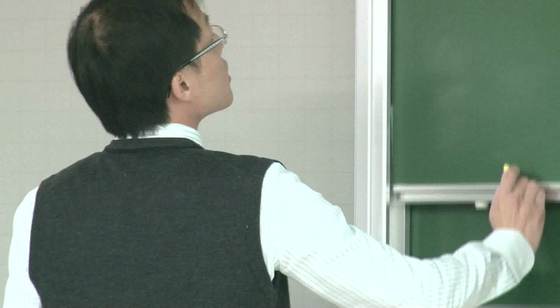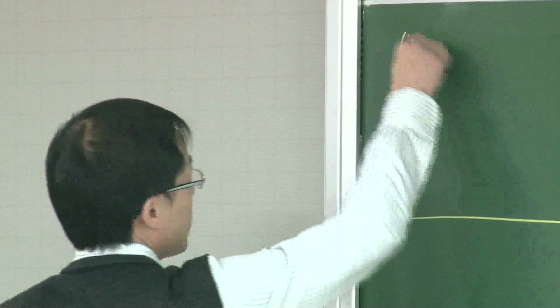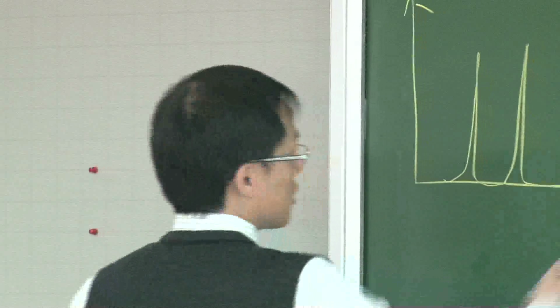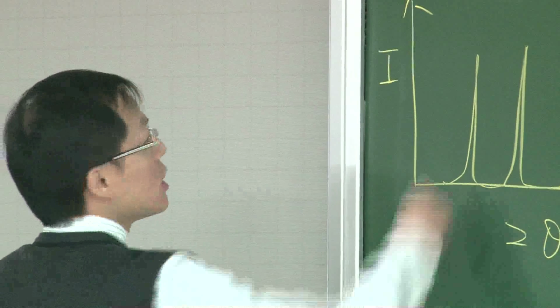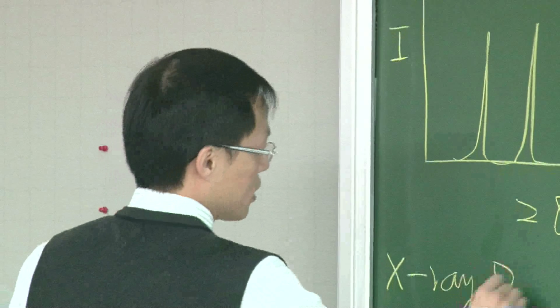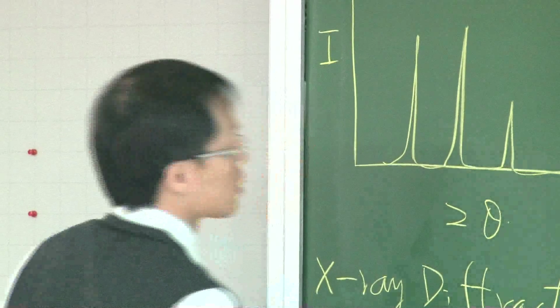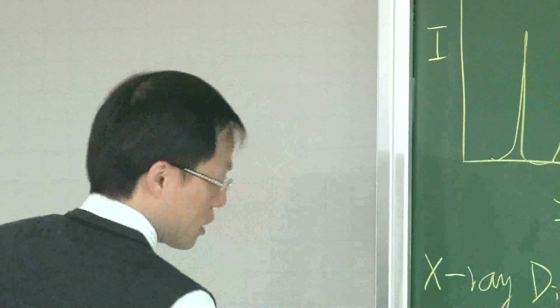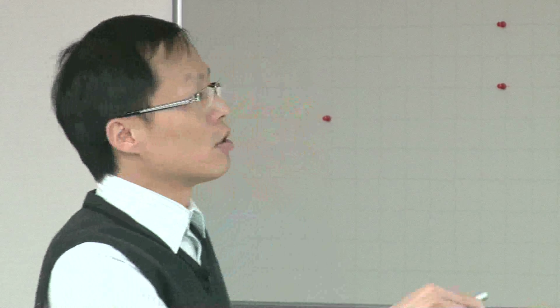So please remember, this is different from diffraction. X-ray diffraction is a long-range ordering technique to probe your structure. That means you need many repeated unit cells, many repeated distances, many repeated patterns. Then you can get a sharp diffraction peak. For an XRD pattern, a diffraction pattern, you have such diffraction peaks. This is 2 theta, and this is your intensity. This is for X-ray diffraction, and for this you need long-range ordering. But the XAFS technique is just a short-range ordering theory.